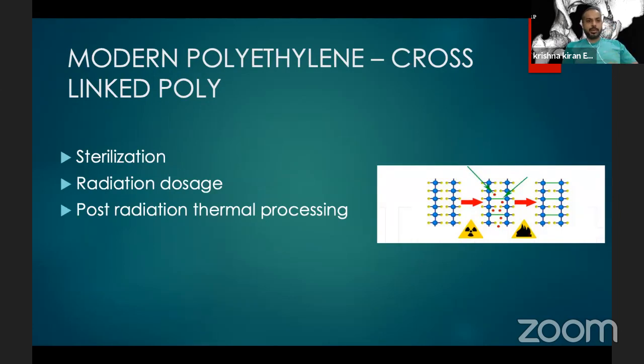And the cross-linked poly is obtained by cross-linking of the conventional polyethylene. And this was an anecdotal or an accidental discovery which happened when they found that when they were sterilizing with gamma radiation, there was some element of cross-linking which was happening, and this had a protective phenomenon on the wear rates.